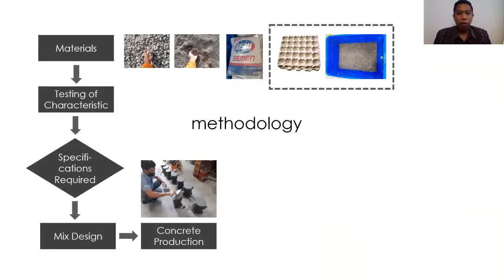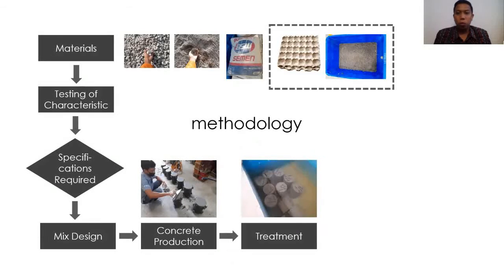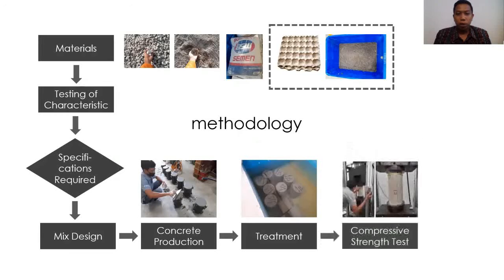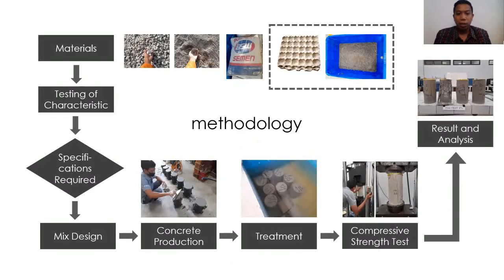The percentage of egg tray addition is based on the ratio to the weight of the fine aggregate. Each sample variation was made as many as 8 samples of cylindrical specimen with a diameter of 10 cm and a height of 30 cm. The specimen was given treatment in water after 24 hours of production, and the compressive strength test was carried out at the age of 7 days and 28 days.